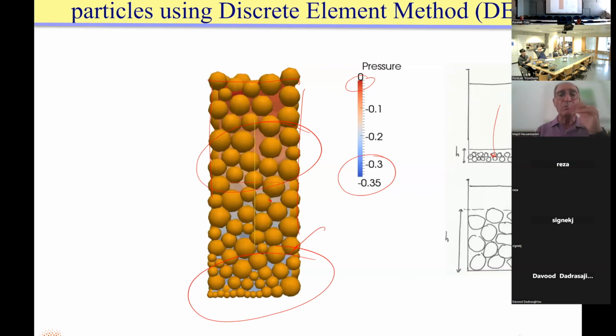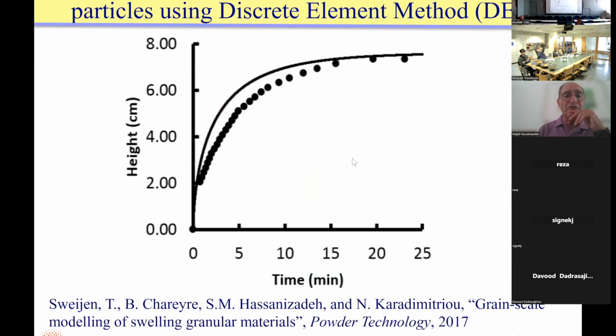So this was all modeled and simulated, and we compared our simulations with the measurements that I showed you. The dots are the height of these rising particles as measured, and the simulation is the line, which is reasonably good. There are ways to improve that as well, actually.